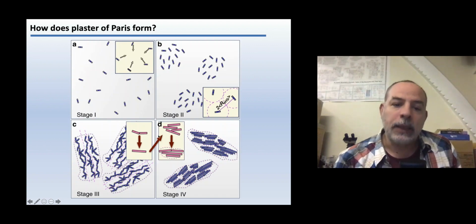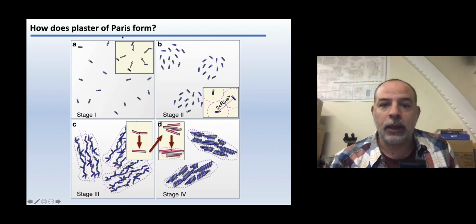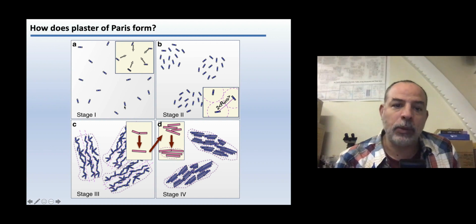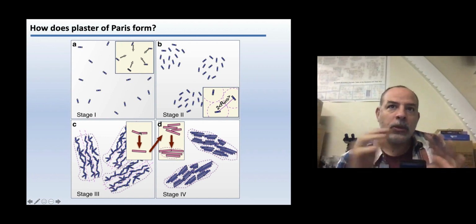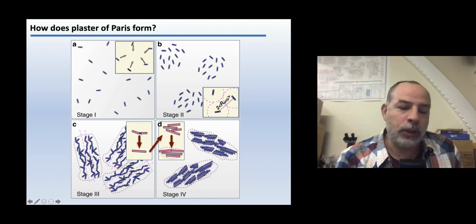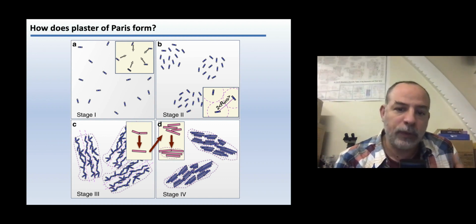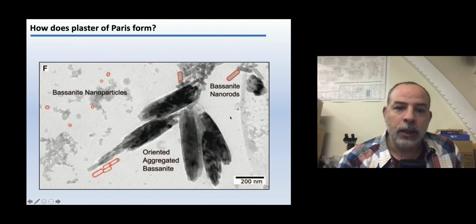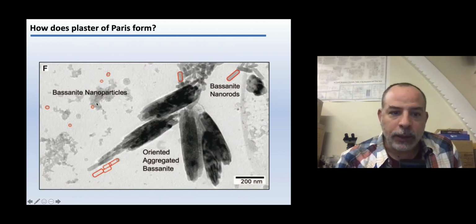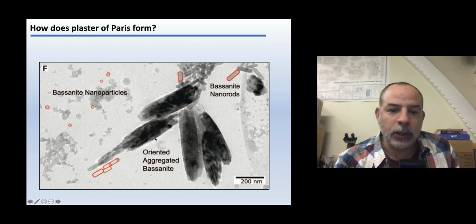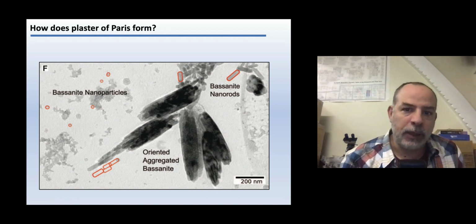Okay, and the process could be summarized by using a schematic diagram like this, in which you see the nanoparticles, nanorods, coming together via oriented attachments, which is depending on energy, on the surface energy, and then later on transforming into gypsum. Okay, and this is what you can see here, nanoparticles of basanite, and then this oriented attachment of these nanoparticles forming, or these nanorods forming bigger basanite crystals. Okay, and later on transforming into gypsum.